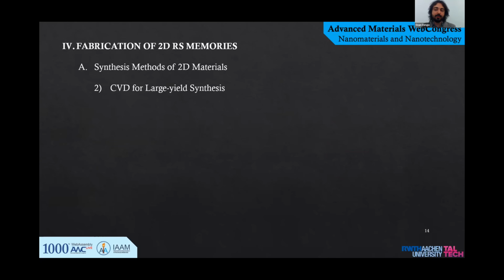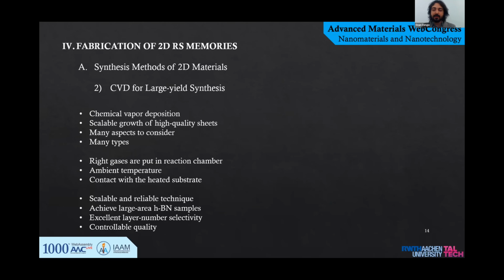CVD is the most promising method for scalable growth of high-quality sheets. There are many aspects to consider, and there are many types of it, but the basic version is pretty straightforward. The right gases are put in a reaction chamber with an ambient temperature, and as they contact the heated substrate, the reaction happens. CVD is a scalable and reliable technique which has the potential to achieve large area h-BN samples with excellent layer number selectivity and controllable quality.